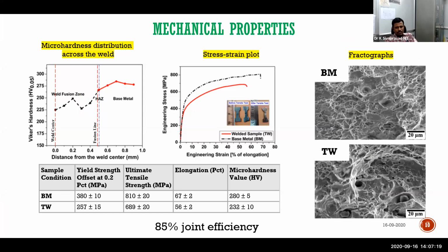When we tested that, to our surprise, normally the fusion zone is supposed to give 50% of its efficiency. That's what we felt. But we got 85% efficiency because we got a single phase FCC fusion zone. Normally it is very difficult to get a welded joint with close to 60% ductility; it is highly abnormal. Base metal you can get very comfortably 70% for these systems, either high entropy alloy, austenitic stainless steel or nickel based superalloys. These are all called low stacking fault energy single phase FCC systems, so they are supposed to exhibit very high strength and high ductility combinations. But fusion zones used to be somewhat disruptive in nature. To our surprise, in this system we got 85% joint efficiency, which is uncommon.